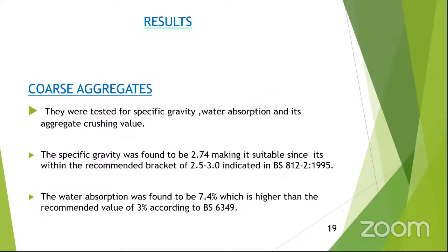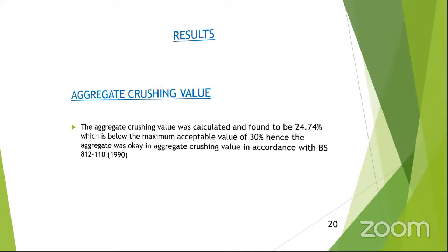In our coarse aggregate, we tested for specific gravity, water absorption, and the aggregate crushing value. The specific gravity we found to be 2.74, making it suitable since it's within the recommended bracket of 2.5 to 3.0 as indicated in British standards 812/1995. The water absorption was found to be 7.4%, which is higher than the recommended value of 3% according to BS 6349, making it inappropriate for use.